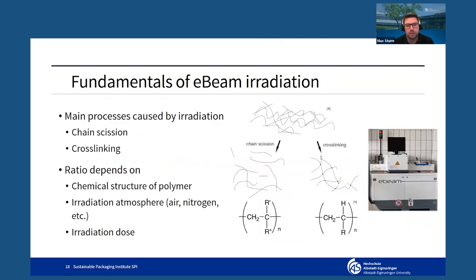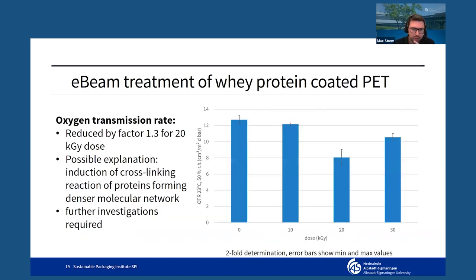So overall, we achieved very good results with these coatings. And to further improve on this, we also applied electron beam irradiation to them. This is meant to induce a cross-linking reaction between the protein molecules to form a denser polymer network, as it's illustrated here, and thus to increase the barrier properties against gases and water vapor. So we applied electron irradiation at different doses, so at different amounts of energy that are delivered by the electron beam to the substrate.